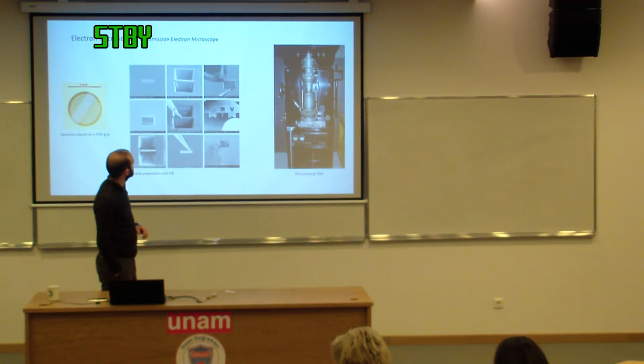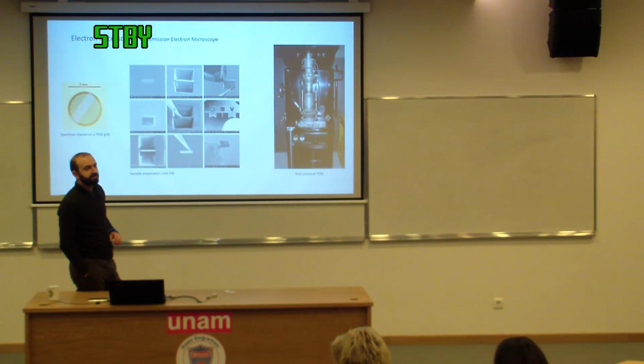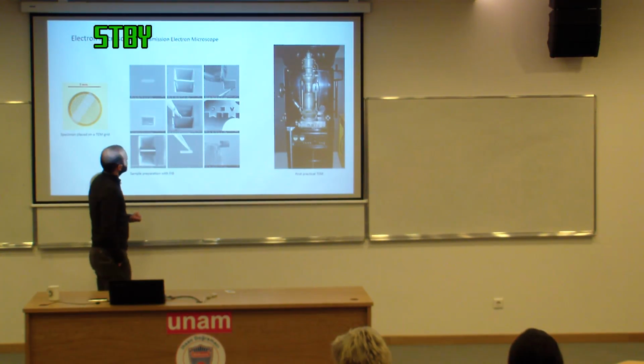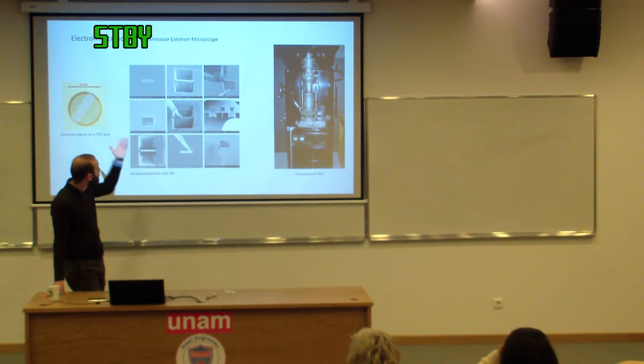So with FIB, the roughness you get afterward matters because for metallic components, electro polishing gives us nanometer roughness. In the case of FIB, typically you don't have any problem in terms of sidewall flatness. There is sometimes gallium penetration into the sample material, but you can always find regions without gallium penetration, because what you're interested in is an extremely small region, and you can always find flat sections of your sample. You don't need to actually polish your sample.